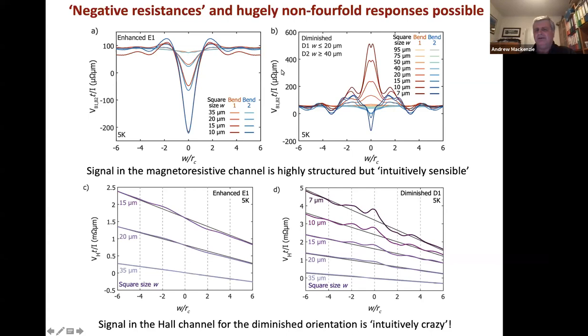But at least you can say one thing. It's fundamentally a measurement of the magnetoresistance. So you are heartened in your mind to see that the signal is even in field, right? It's symmetric as you make the field negative. Then you go to the enhanced orientation and you measure the Hall effect, and you see deviations from an ohmic Hall effect, which again is what you would have expected. But you're heartened to see that that is an odd thing. It's antisymmetric in field.